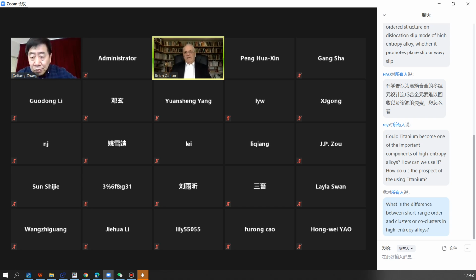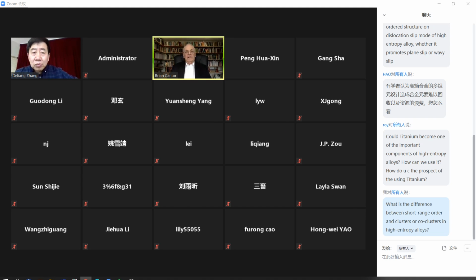So in that material, there is no short-range order, but of course the dislocation slip still shows all these characteristics. The dislocation slip is not easy, and you have this because of the local lattice, the local atomic structures, and the local lattice strain. It's not enough lattice strain to change the short-range order, but it is enough lattice strain to restrict the dislocation slip and give you pretty high, not super high, but pretty high basic yield strength. And then, as you rightly say, work hardening.